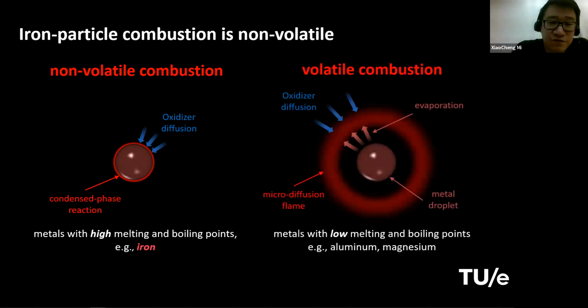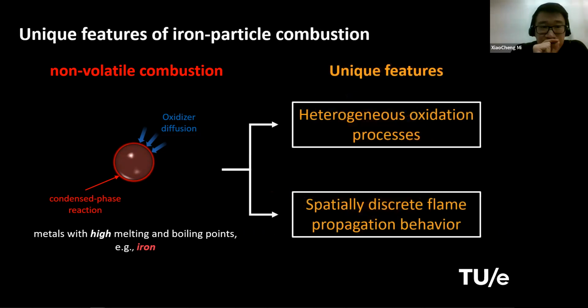And this is quite different from some other metals like aluminum, magnesium, which have a relatively low boiling point so that their combustion is volatile, wherein you evaporate the fuel first and then most of the energy release happens in the gas phase. And because of this unique feature of iron combustion, it gives out some very unique characteristics or very unique problems that we need to solve with iron dust combustion.